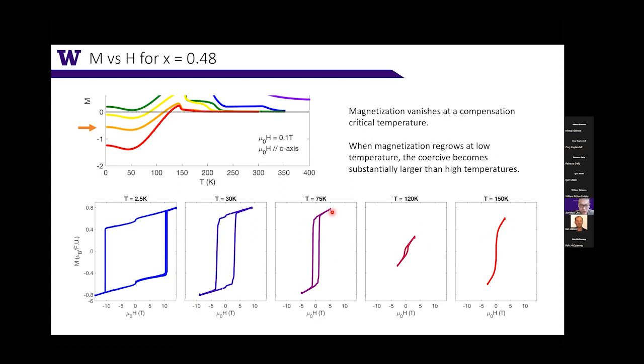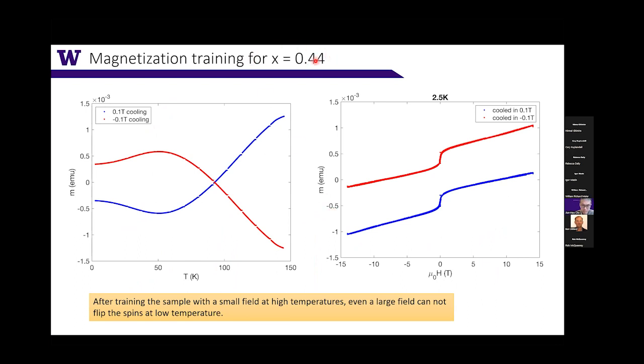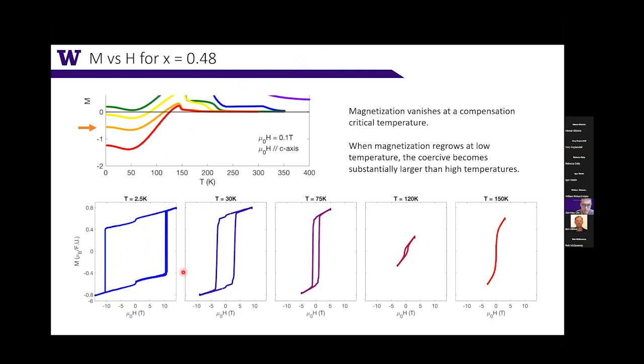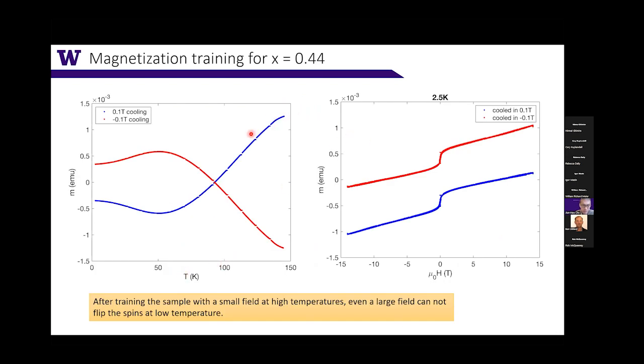However, this allows us to create some very interesting states. For example, in this slightly lower doping where you have an even larger coercive field, at low temperature the coercive field is beyond 14 Tesla. You can cool at a small positive or negative field, and see the magnetization reversal at this intermediate temperature. Then you apply a large field at low temperature, and you can see that the state is frozen in this opposite magnetization state. For example, cooled in negative 0.1 Tesla, you get a positive magnetization, and even if you apply a field, it's frozen into that state and you cannot flip the magnetization, or vice versa. And we don't really know what's going on with this very small, soft paramagnetic behavior at low temperature at this point.